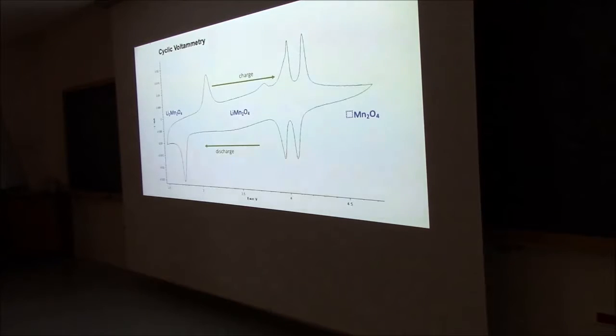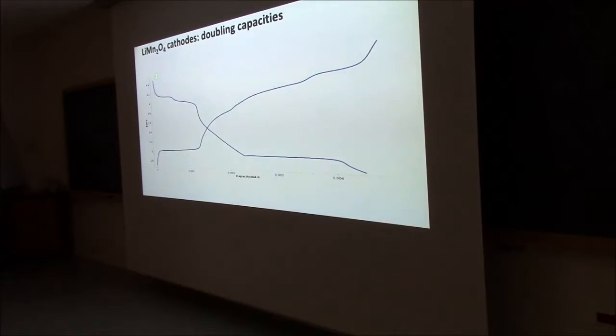Of course, we have these thin films, so at some point a student said, let's give it a try. Normally, we're studying these peaks around 4 volt, but then we went down to 3 volt and back up. And these are the 2 peaks connected to that. You can see the distance between them, so there is some internal resistance, but this was not too much. But you can see strong peaks, so there's a lot of current there, there's a lot of capacity. So if I put this in the other picture, this is what we get. This is normally the capacity that we're taking out, and then we go to 3 volt, and you can see we at least have the same plateau there. So we're pulling out double the capacity.